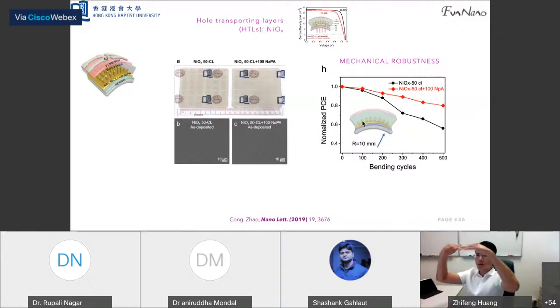Mechanically, we bend the flexible solar cells and we measure the PCE, the photo conversion efficiency. Let's take a look at the black curve. After 500 bendings, the PCE has degraded roughly 40%. But when we have the nanopillars, the PCE only degrades around 15% after 500 bendings. So the mechanical robustness has been significantly improved.